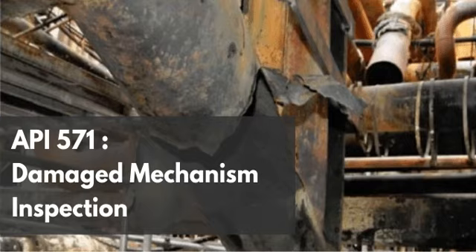You absolutely cannot use brute force mechanical grinding. So what do you use? Surface prep for ACSCC requires light, localized, abrasive blasting, like a gentle sweep blast. Or you use highly specialized, non-loading abrasive wheels that remove oxides without generating the shear force required to smear the matrix. It really requires a technician who fundamentally understands the metallurgy of what they're touching.